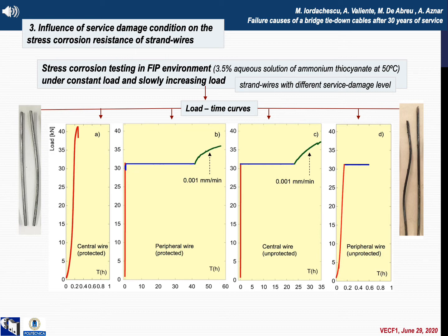Figures B, C, and D show the test results as load time dependency. The curve in figure A has been added as a reference and corresponds to a simple tension test. The stress corrosion under constant load tests illustrated in figures B and C were interrupted when they far exceeded the minimum required surviving time, but the wire specimens were subsequently subjected to constant extension rate tensile testing until failure in the same environment.